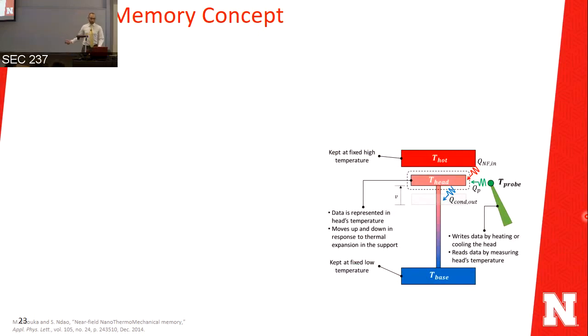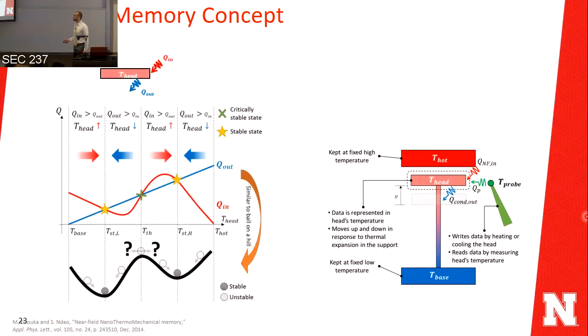So how can you achieve a thermal system with two stable states? You need to have nonlinear heat transfer to the head. This is the head, and this is the heat input, and the heat output. The heat input is from the near field thermal radiation between the head and the hot terminal, and the output heat from the head would be the heat conduction through the support. If you need a system with two stable states, you need one of these heat components to have nonlinear interaction. The conduction has a linear profile with the head temperature.